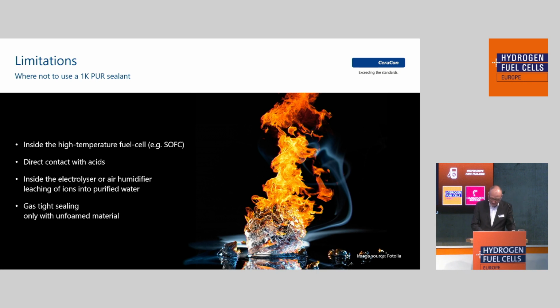Foamed polyurethanes cannot be used as a seal for hydrogen. This is independent of single or two-component materials or any other foamed polyurethane. Because of the cell structure of the foam, the small molecule hydrogen will always migrate through this foam. So this cannot be used for hydrogen, but of course there are other applications we can solve with this material. Other limitations, as you can see here: it's not possible to use it inside the high temperature fuel cell, SOFC, so solid oxide fuel cells.